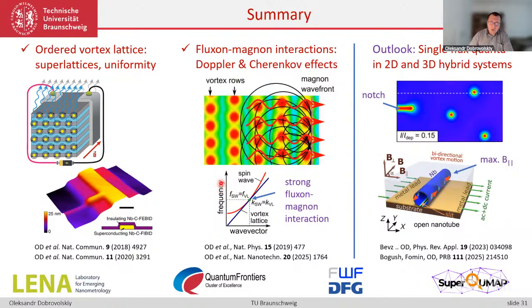The physical meaning is a matching of energy and momentum, or frequency and wave vector, in other words. So the condition of self-synchronization, or the condition of Cherenkov resonance, for strong fluxon-magnon interaction, with wavelengths of the order of 35 nanometers as record values achievable so far. And we are developing approaches towards single flux quanta and the operation in 2D and 3D hybrid systems, meaning that further hybrid systems should emerge also on the basis of these platforms. So this brings me to my conclusions, and I'm very much open to your comments and questions.